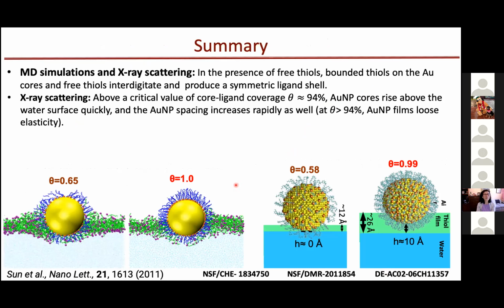So in summary, the MD simulations and X-ray scatterings both show that in the presence of free thiols, bonded thiols on the gold cores and the free thiols interdigitate and produce a symmetrical ligand shell. In addition, the X-ray scattering shows that above a critical value of theta, about 94%, the gold cores rise above the water surface quickly, and the gold spacing increases also very quickly. That 94% happened to correspond to the point above which the gold film seems to lose elasticity.